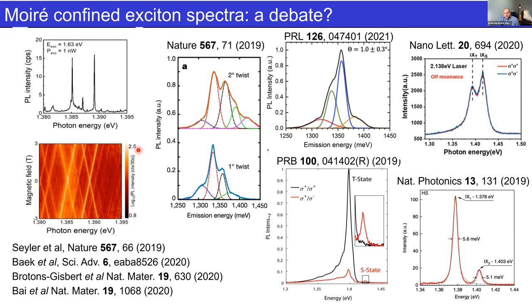But the basic idea is that there are much broader peaks, about 100 times broader than what I've just talked about. So about 5 meV in the best case, maybe 10 meV is quite typical. And there are also multi-peak spectra. This has opened a debate, at least if I read the referee reports, about whether these are truly Moiré excitons, or whether they are just trapped in some sort of defect. So we wanted to investigate this a bit more closely.